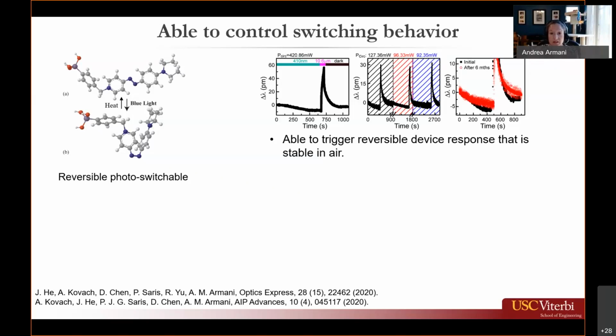As you can see in this first data set, when we exposed it to 410, we got a negative blue shift. When we exposed it to 10.6 microns, so it's a CO2 laser, we were able to thermally heat the device surface, which initiated the red shift, and then it recovered when it was able to relax back. We were able to do this on the same device multiple times. Additionally, one of the concerns you have with an organic molecule is its stability in air. Organic molecules are notorious for degrading over time and when stored in air. So this is a pair of results that we took. The black is the initial results, and the red is after we stored the device in air for 6 months and then retook the data, and we got the same results.